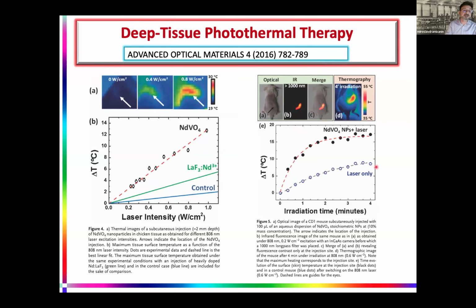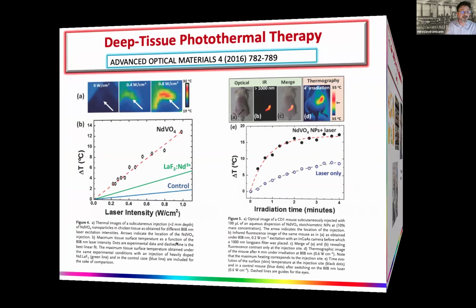And on the right side, you can see thermal measurements. After 4 minutes of irradiation, we raise the temperature, and we use neodymium 3+ as a Boltzmann thermometer to measure the distribution of temperature inside the cancer. So this luminescence can serve as an agent for luminescence imaging, as an agent for biothermal imaging, and also as a photothermal agent to produce heat inside the biological environment. There are some examples of intracellular measurements. People today are able to measure temperature distribution inside the cell. And let me just point out that when you have gadolinium inside, it can also serve as a T1 positive magnetic resonance imaging agent. So they are very versatile nanoparticles.